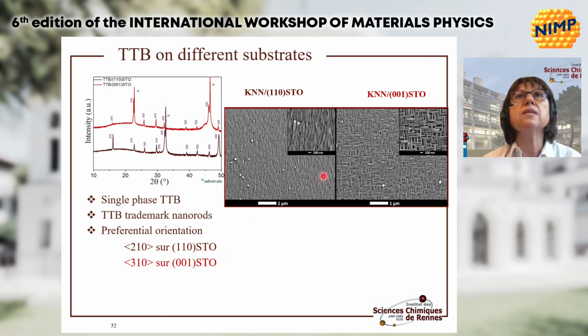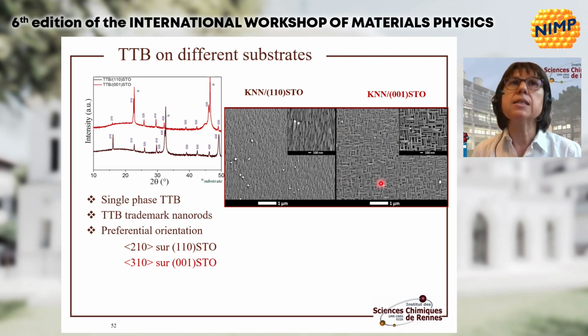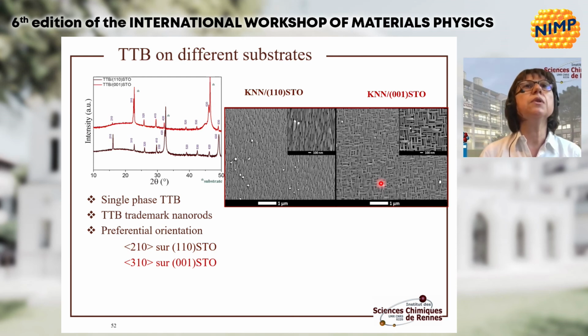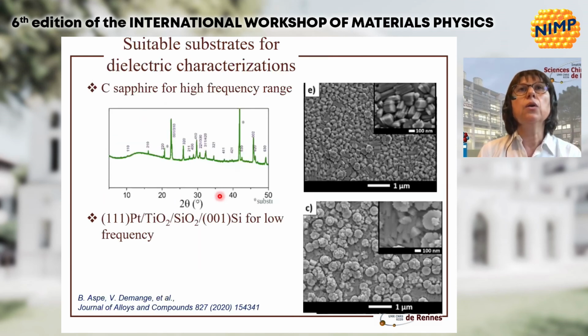On 110 STO, as you can see here, there is only one in-plane orientation, and two types of orientation on 001 STO. So it's possible to control the epitaxial growth of such films. Now, on sapphire, for high-frequency measurements, sapphire is desired. Thin films have been deposited on C-sapphire for the high-frequency range.